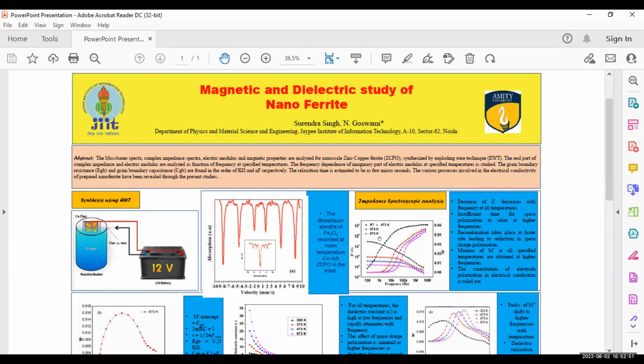There is no contribution of electrode polarization in the electrical conduction process of zinc copper nanoferrite prepared by the exploding wire technique. And since the plot of M double dash, the imaginary part of the electrical modulus, versus the real part of the electrical modulus has only one arc, the grain boundary plays a vital role in the electrical behavior of the prepared sample.